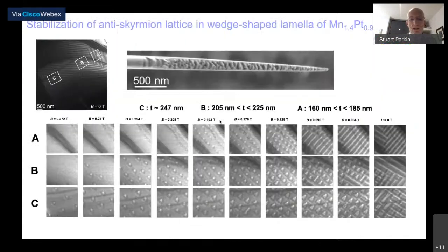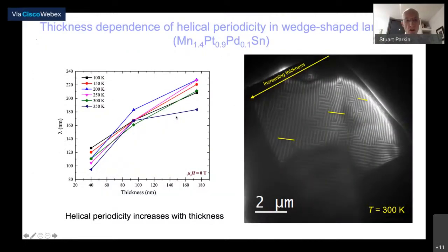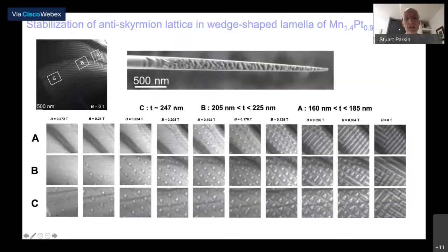Okay, so now I want to talk about another very interesting aspect of these anti-skyrmions, which is what happens when we change the thickness of the lamella through which we are directing this electron beam. And I want to show you then, first of all, if you look in the middle, this is a scanning electron micrograph of a lamella, which is a wedge-shaped lamella we formed by focused ion beam milling. And on the left side, you can see the Lorentz transmission electron micrograph in zero magnetic field.